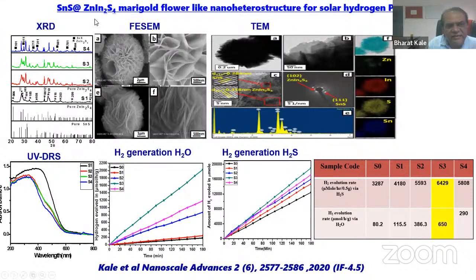Then in the same way we did SnS decoration on ZnIn2S4. We found that there is a ZnIn2S4 plate, and in between there is an SnS plate. So one SnS plate is sandwiched between two ZnIn2S4 plates. It's a very beautiful structure we observe. Because of this sandwich nature of SnS, the suppression of recombination of the electron-hole pairs is much higher in this case because of the uniqueness of the structure. We found a great enhancement in hydrogen production with SnS decoration.